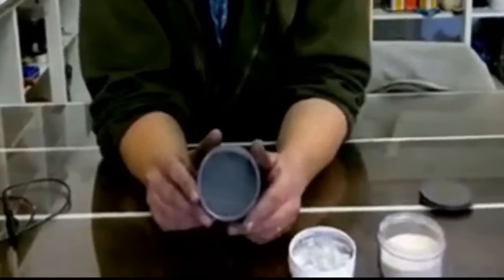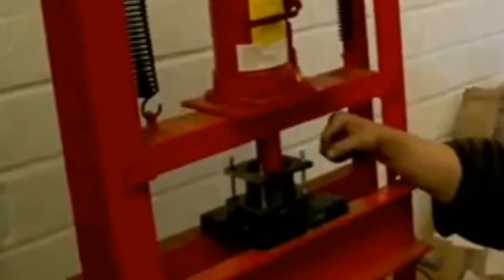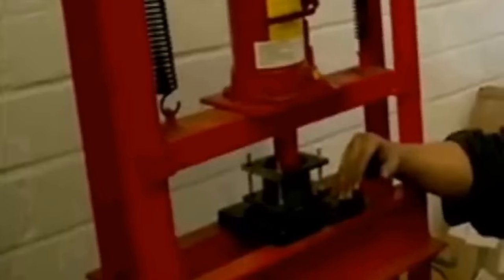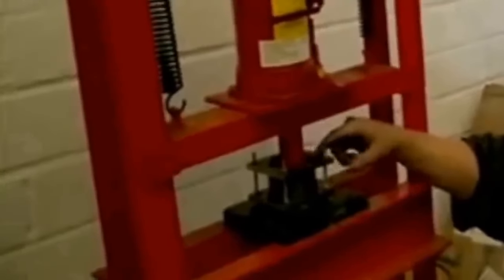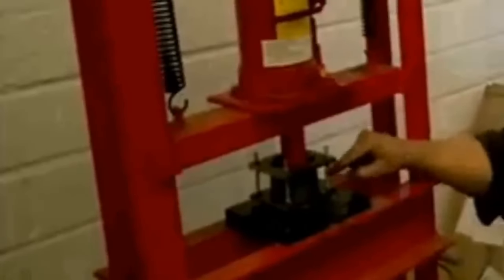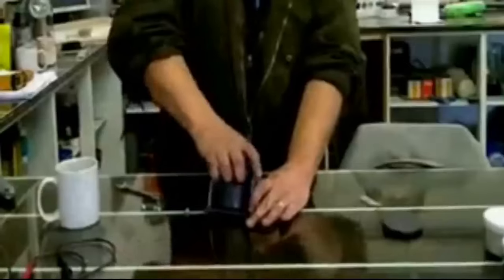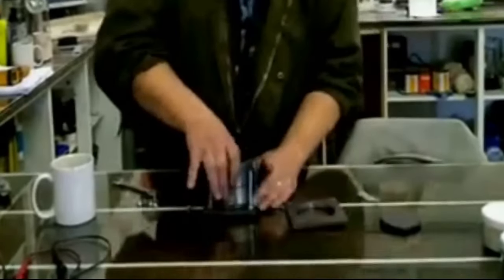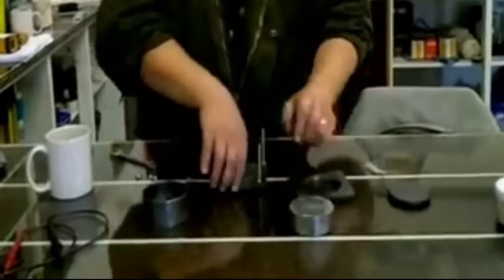What we do with that is put it into a mold. Now, a mold is really simple. It's just a press and a bit of steel. And you pour the powder into there and heat it to 135 degrees centigrade and then put about 20 tons on it, which is what this press is. When you've done that, you can take it out of the mold. And there is our piece of plastic.